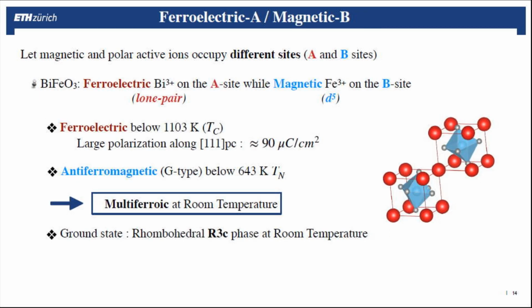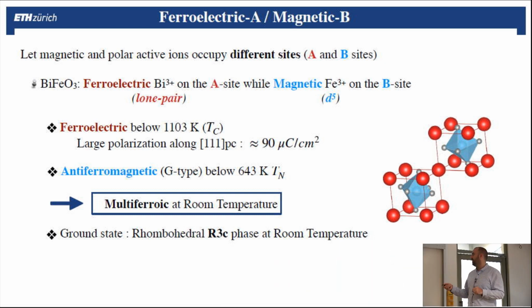The opposite example is bismuth ferrite, which I will spend some time on. So bismuth ferrite is a ferroelectric material and also magnetic. It is ferroelectric below 1100 Kelvin, and it has a large polarization. This is a large value if you're not used to polarization values. And it is antiferromagnetic G-type, so the same as the other one. The neighbors in plane and out of plane have opposite spin direction.